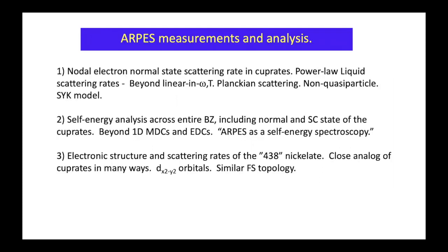Okay, so these are the three topics for our ARPES measurements. I'm going to start with the nodal electron normal state scattering rates in cuprates. What we show is our power law liquid scattering rates. So we're all very familiar with the linear in omega and T scattering. We argue this is only linear at optimal doping, sublinear for underdoping, and beyond linear, supralinear.